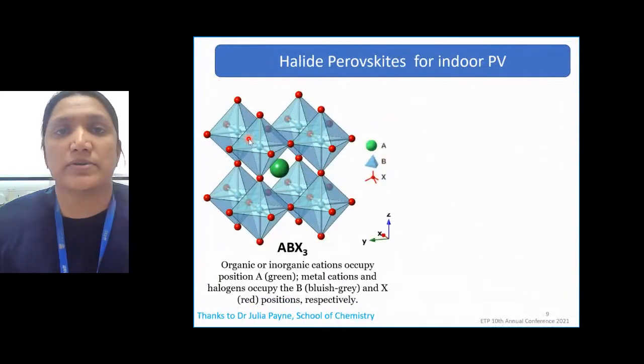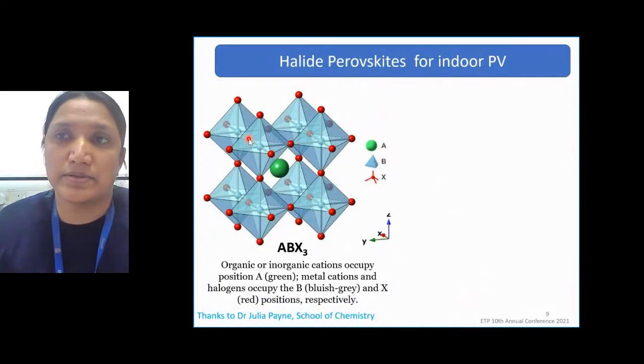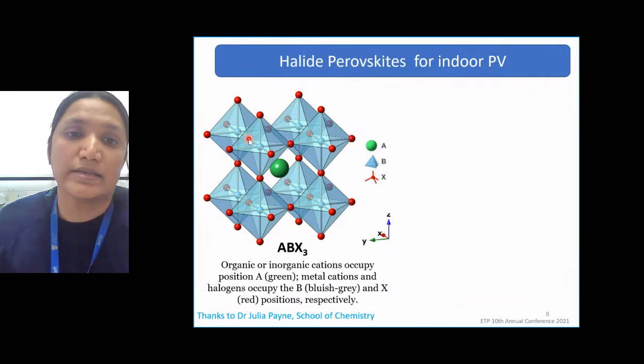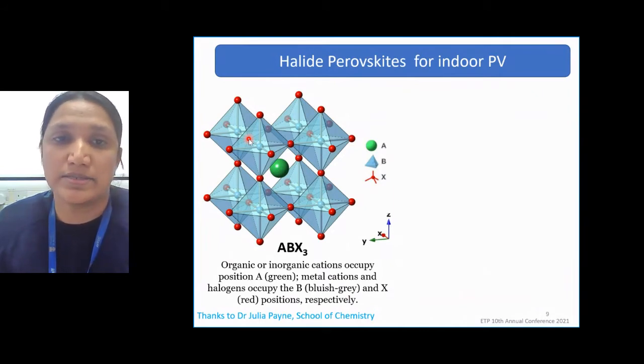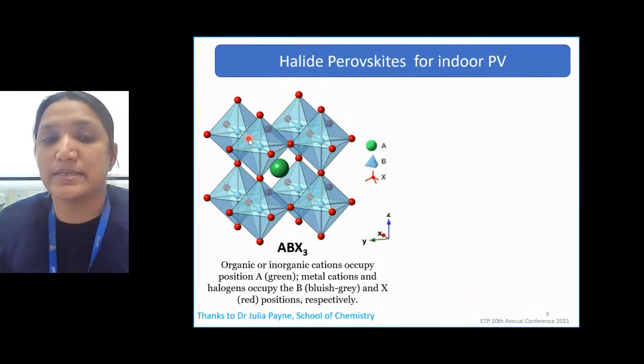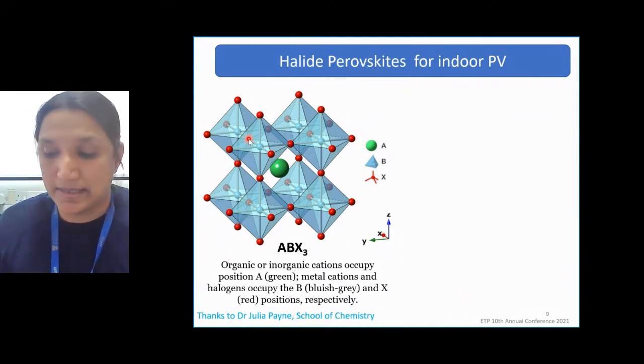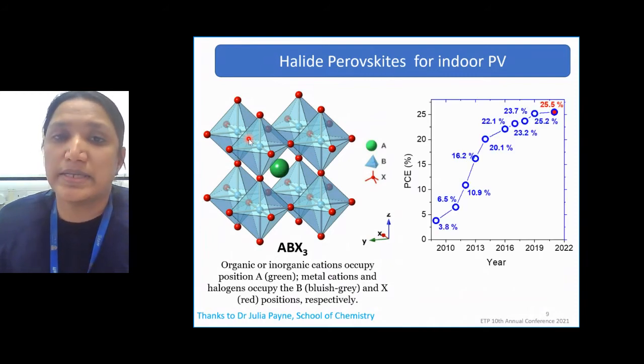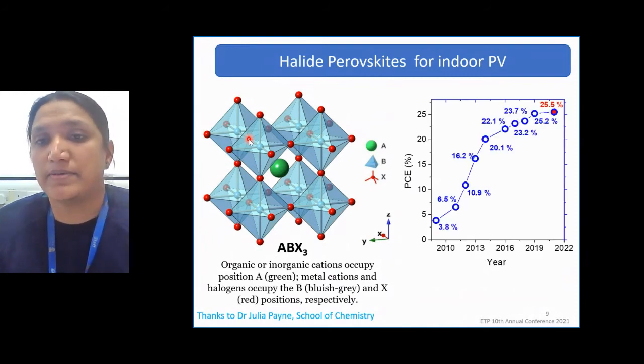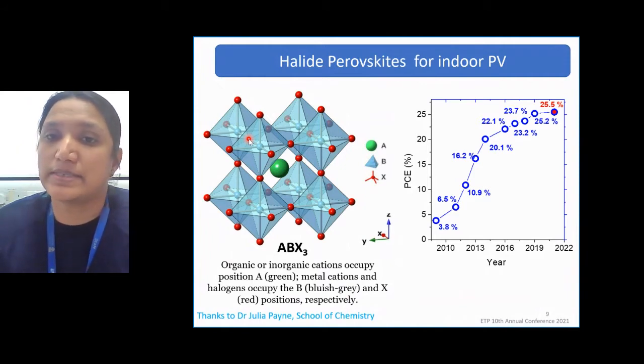Among the various photovoltaic materials available today, halide perovskite semiconductors are particularly interesting and most promising for indoor light harvesting because of their excellent light to electricity conversion properties and their band gap tunability. They are easily solution processable, so scalability is good, and they have excellent optoelectronic properties such as a high light absorption coefficient, as well as much higher charge carrier mobility. And these materials have already demonstrated a certified power conversion efficiency of more than 25% under one sun illumination.